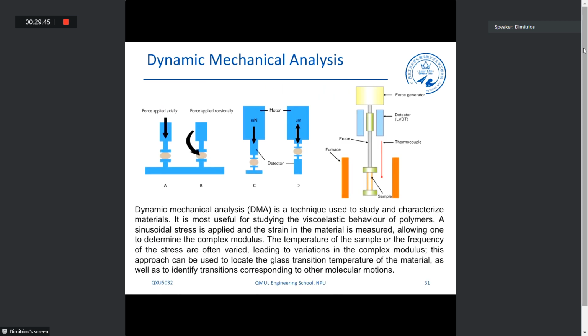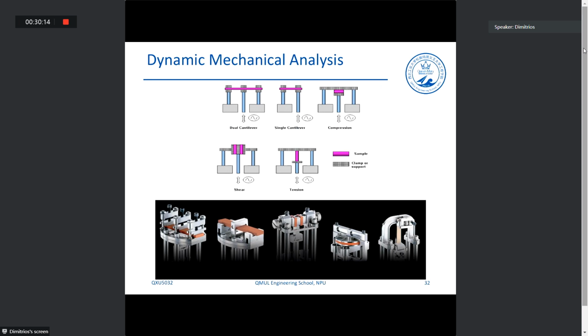What do we do in a dynamic mechanical analysis experiment? Essentially, we apply sinusoidal stress and we measure the complex modulus. We observe the response of our polymer to the sinusoidal stress. What we can do usually is vary the frequency of the measurement. So we usually vary either the temperature or the frequency of the measurement in order to obtain a graph of modulus versus temperature for different types of material. Now, there are different types of holders that we use, where the purple thing is the sample.